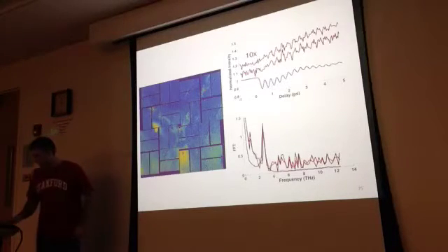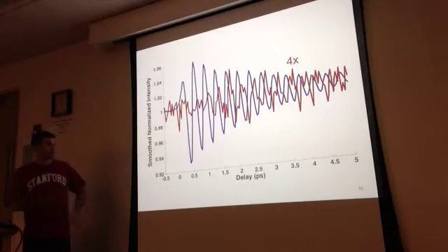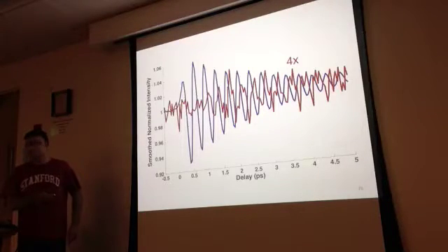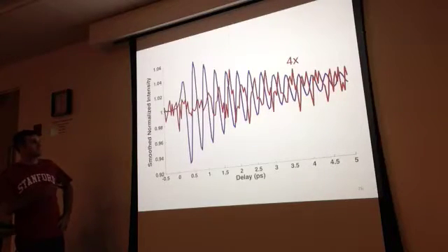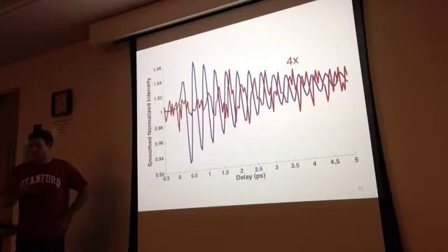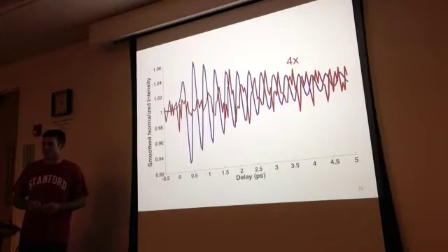So just to try to convince you further, these are those same curves where I've removed a moving average. You can see that the blue curve is oscillating at first very strongly right at time 0, and all it does is spend the rest of this time decaying. While the red trace isn't doing much at all at the beginning, and then oscillations start and amplify as it gains energy, or energy is being pumped into it from the blue mode. And you can also see that these two are about pi over 2 out of phase, just as you would expect for a driven oscillator.